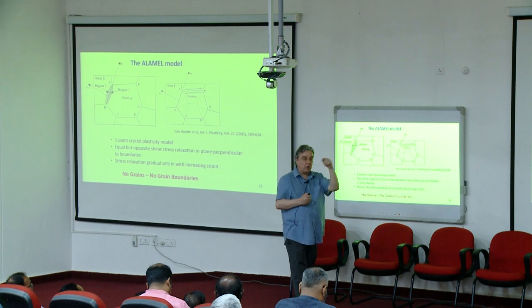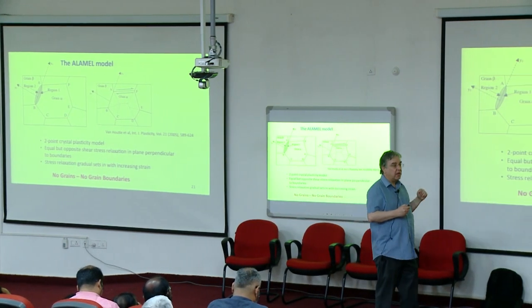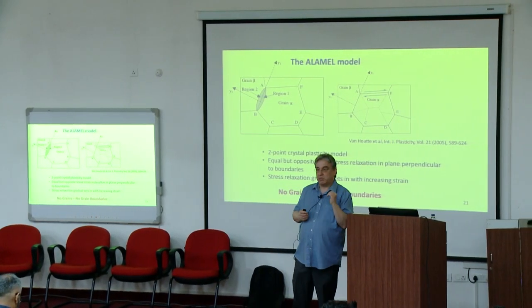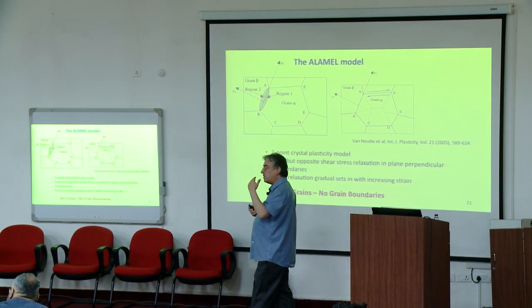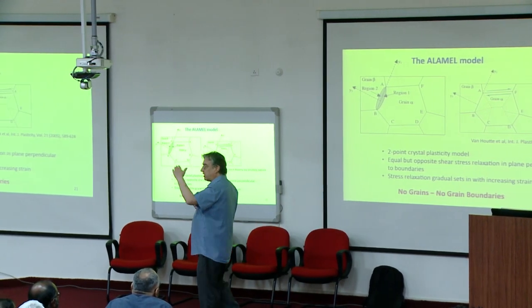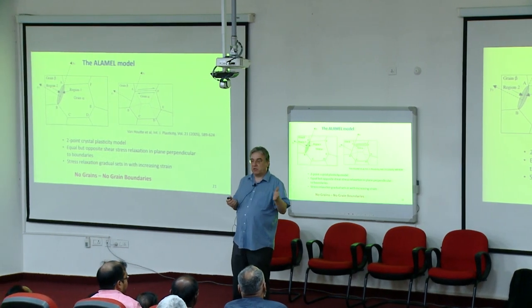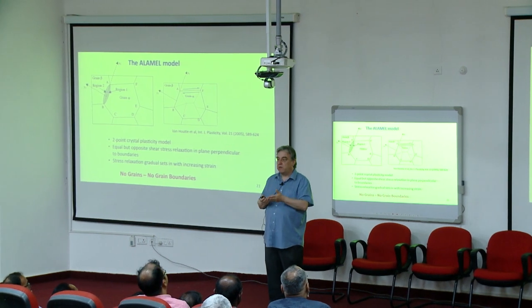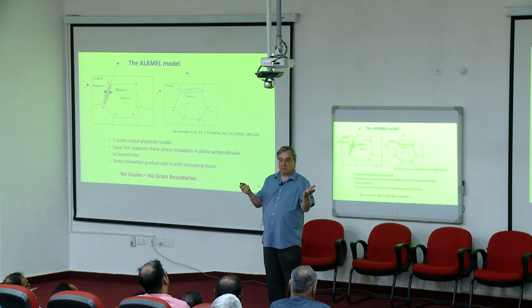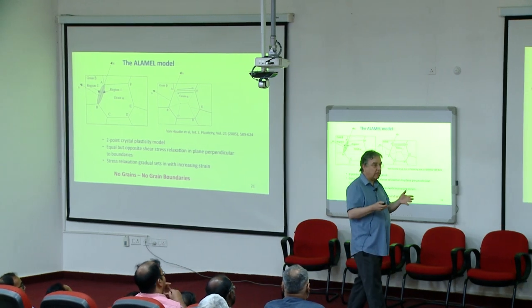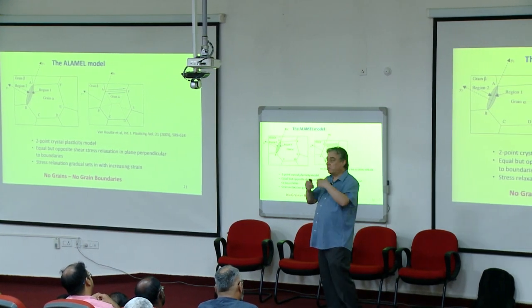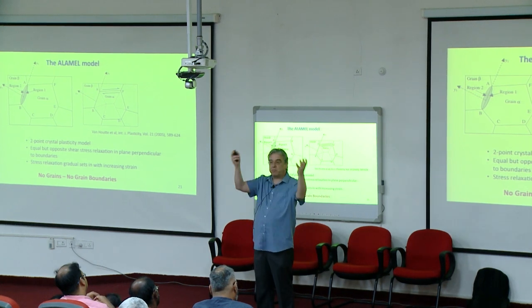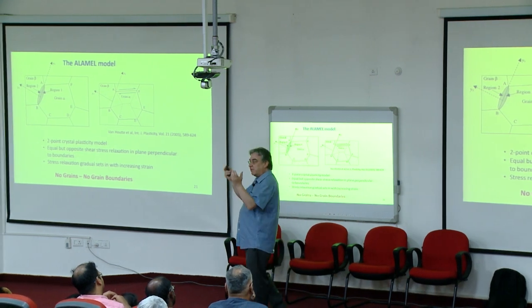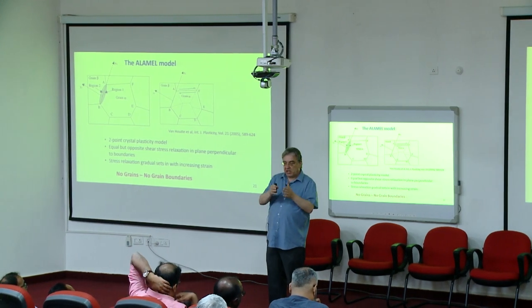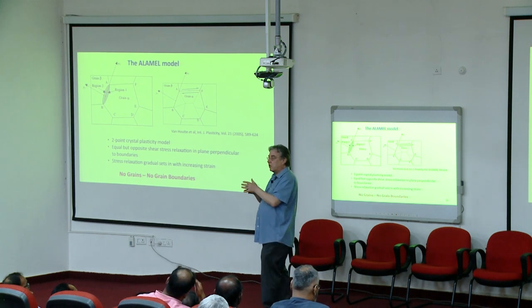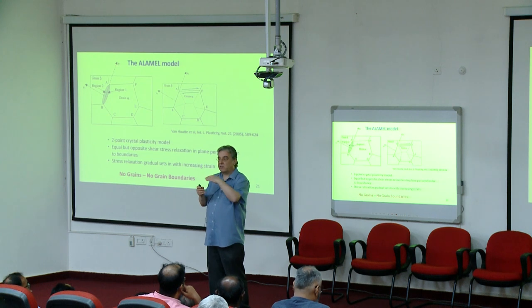However, if you go back to the atomic level, a little bit beyond the border of continuum mechanics, things are not so simple, because on the atomic level, we know that metals deform primarily by gliding dislocations. Dislocations glide on specific crystal planes in specific directions. For example, in FCC, the dislocations glide on {111} planes in <110> directions. And this is not continuum. There is a finite number of crystal planes and crystal directions, which we call slip systems, that can accommodate plastic deformation. So how do you combine this macroscopic world of rather arbitrary plastic deformation in all directions with the atomic world, the crystallographic world, the rather quantized way of strain?